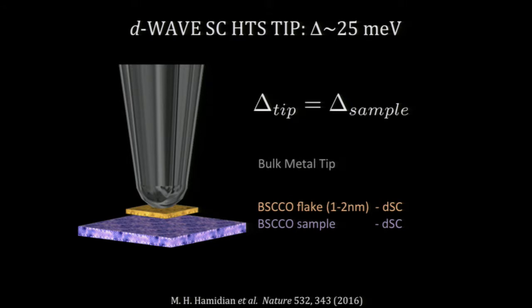Okay, so first challenge: make the tip a superconductor. And you say, well, that's kind of easy. You pick up a metal which is a superconductor. Well, the problem is, if you pick up, let's say, lead, that has, in the low kelvins, that's its transition temperature. So that makes it more difficult. You want a superconductor which has a very high transition temperature. So we developed a recipe by taking a regular tungsten tip and very elegantly jamming it into the surface and picking up a flake of BSCCO. And it turns out that that flake on top of the tungsten ends up being a superconducting tip. So now you can actually create a Josephson junction between your tip and your sample.